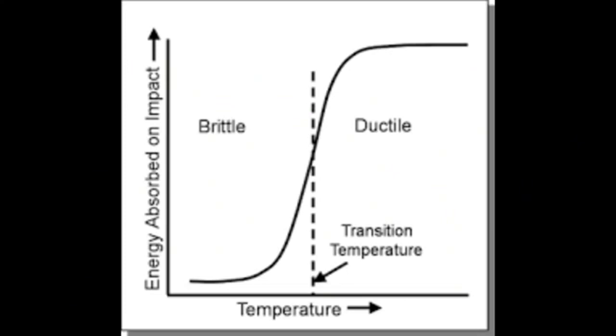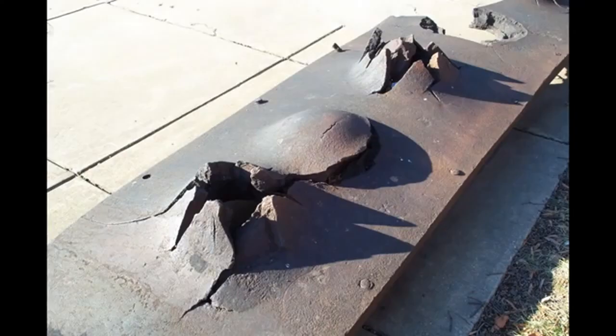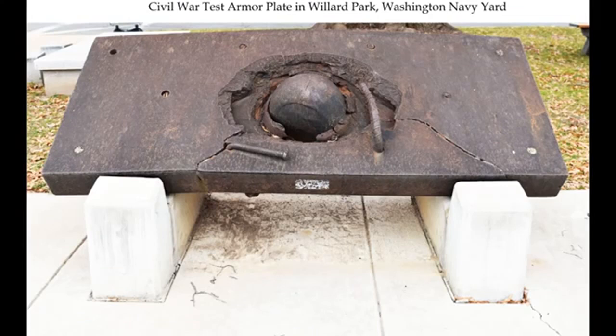Well, it was this change in temperature. A sheet of iron set up on a grassy field on a summer's day would be considerably warmer than practically any metal sheet built into the side of a ship that was then placed in a cold ocean. In some very warm environments, such as the shallow coastal waters off China, ships like the East India merchant vessel Nemesis had still seen ductile behaviour, but in the more common deep ocean environment that covered most of the planet and the North Atlantic haunts of most of the major navies at the time, the brittle behaviour was experienced, which not only meant that iron ships would resist shot far less well than expected in the first place, because of that lower impact energy, but the damage caused would also be far greater.